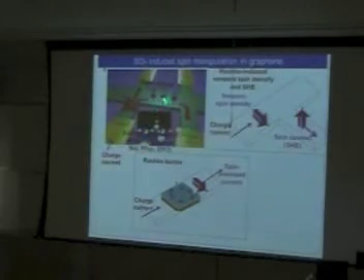By hydrogenation, that is, by mixing some sp3 character into the sp2 character of the pi band of the Dirac electrons, they are introducing spin-orbit effects, a sort of skew scattering, that gives rise to a spin current by the spin Hall effect, and that can be detected by the inverse spin Hall effect and seen as a voltage between the two ends of the stripe. So these are interesting experimental results.